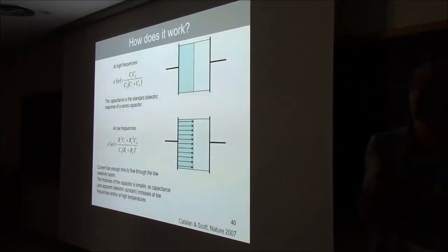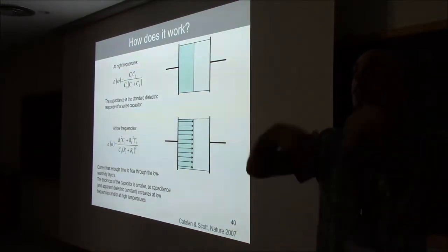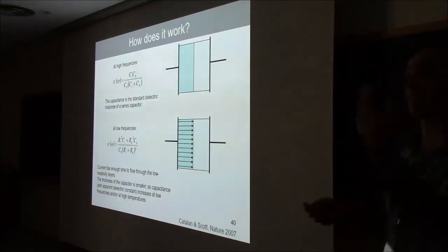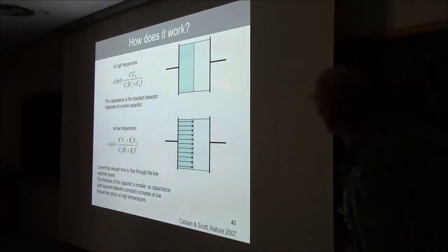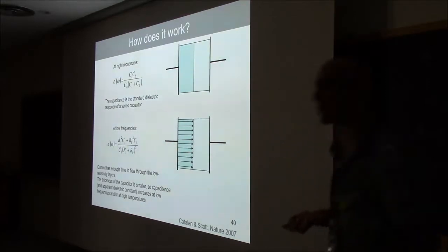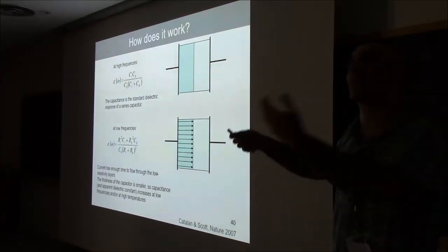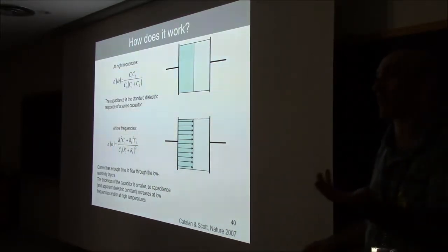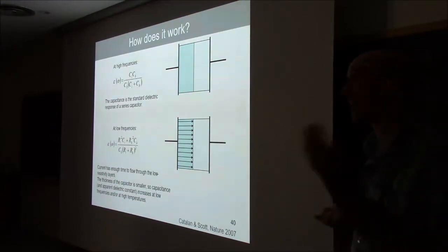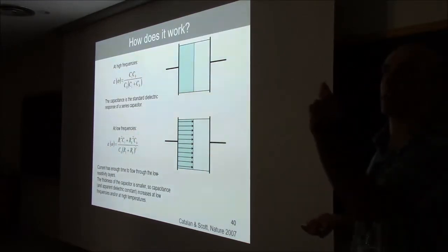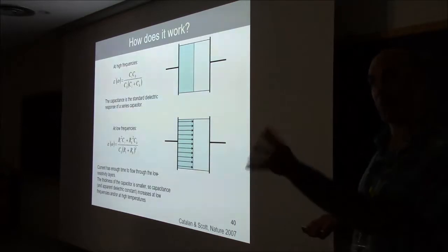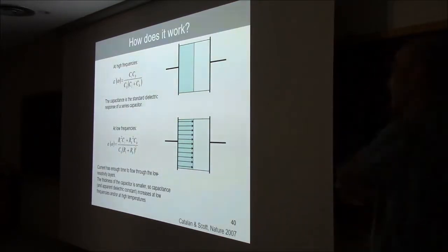And because capacitance goes as 1 over thickness, the capacitance goes up. If that very high capacitance you multiply by the total thickness of your capacitor, you think that you have a very high dielectric constant, but it's not. It's just an artifact that comes from the fact that the actual insulating part of your sample is very thin. Is that more or less clear? Yeah? Okay.